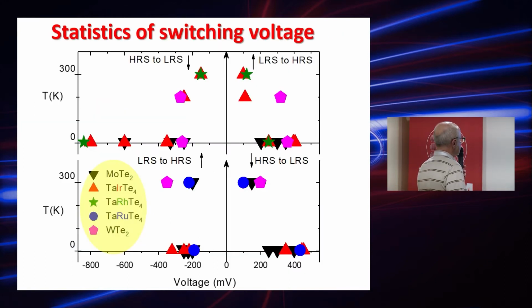So here is a statistic of the switching voltage. Switching voltage is different from contact to contact, but nevertheless it's in the range between 800 and 200 millivolts. And here are also shown the samples for which we observed this switching effect. Additionally to the molybdenum and tungsten ditelluride, we observed this effect also for these 3 compounds which have a similar crystal structure, where molybdenum or tungsten is replaced by tantalum iridium, or tantalum rhodium, or tantalum ruthenium.